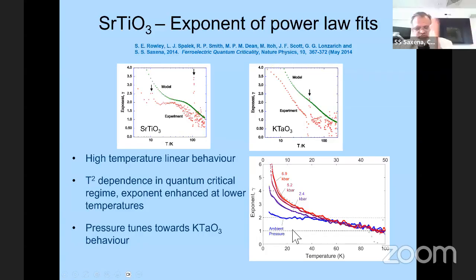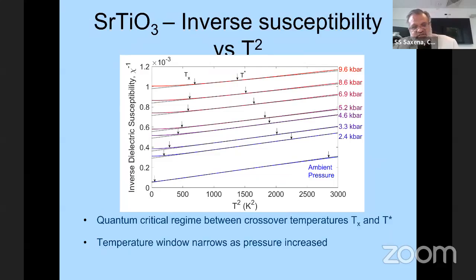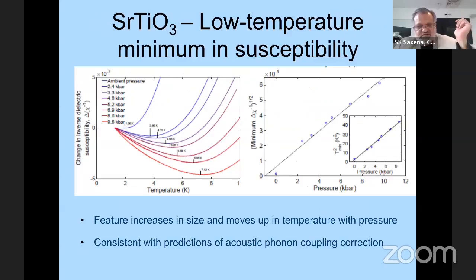So this tunability of quantum states in these materials is a phenomenon which we are quite happy to establish. But there are some other aspects in the final thing that I want to end today by. So this is just to show you that if you're at ambient pressure, this is your quantum regime. You can tune it. Normally one thinks that when we tune it, we increase the quantum space, but depending on the material, you can actually reduce the quantum space, make it more classical, but that doesn't make it less interesting. Why? So if you look at this low temp 2K state that I showed you,